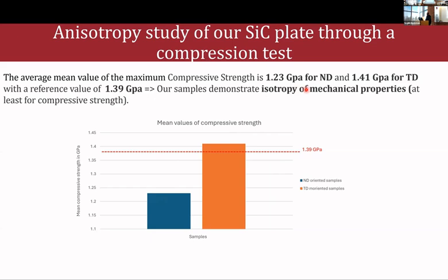And for the samples following the transverse direction, we had a maximum compressive strength around 1.41 gigapascal, with a reference value of 1.39.